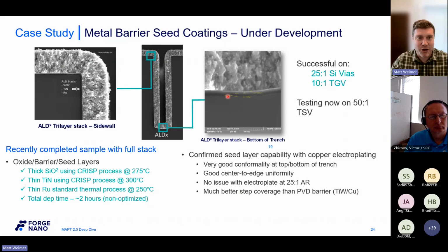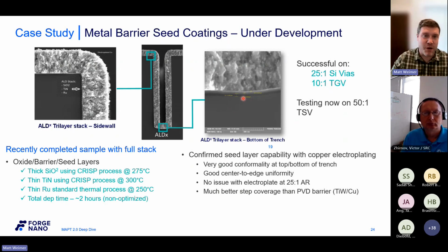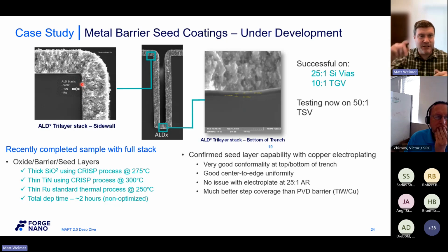I have shown you that there is actually ALD film here. The thicknesses don't really matter. This was done with cross-SEM data that was not of proper resolution. But I also want to show that they did some etching here, some Bosch etching to make these features, so you get those typical scallops. The ALD film is conformal over those scallops, which is, I think, pretty cool to see. Again, very high quality. We've done this successfully on the 25-to-1 silicon vias and 10-to-1 through glass vias. We're testing even higher aspect ratio features, up to 50-to-1.